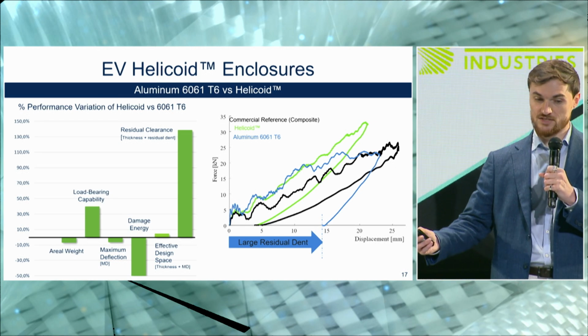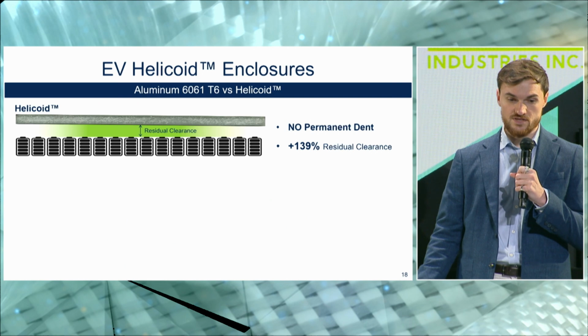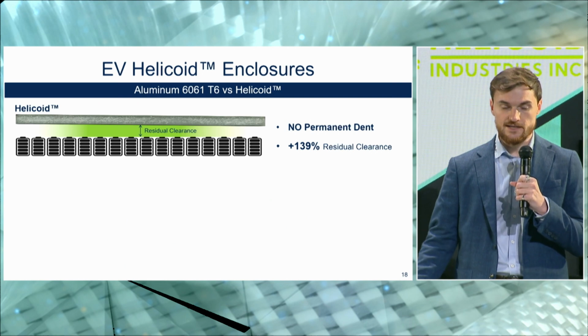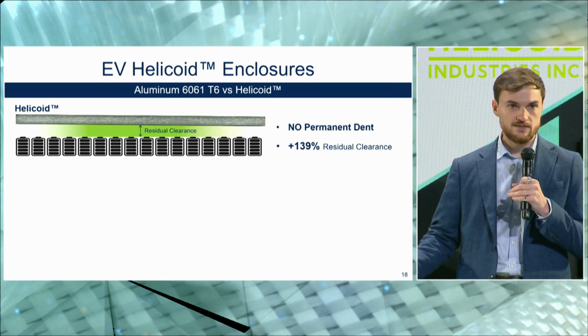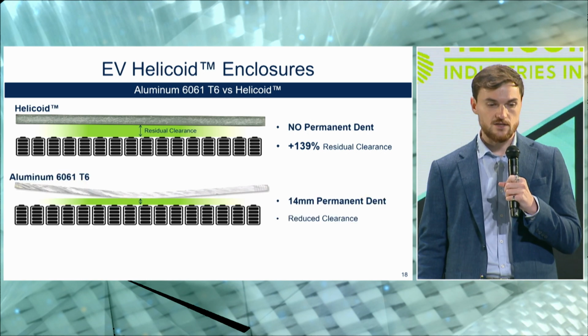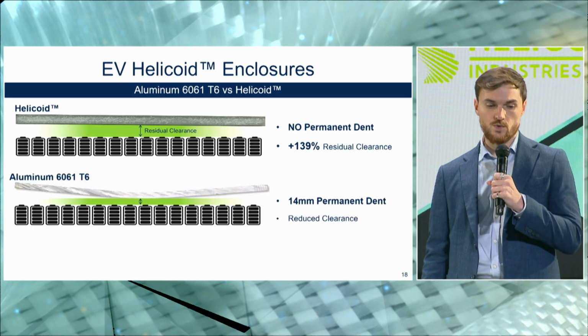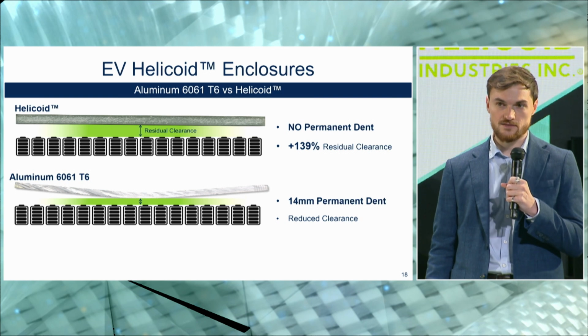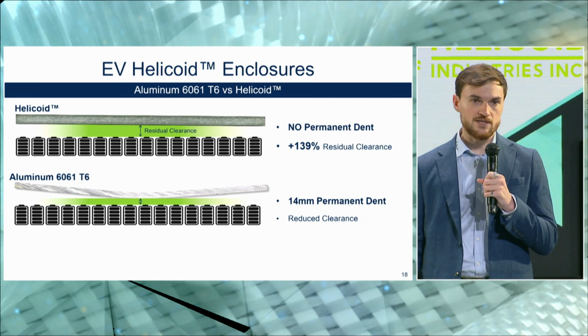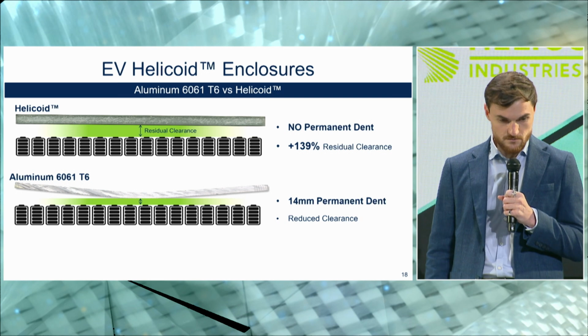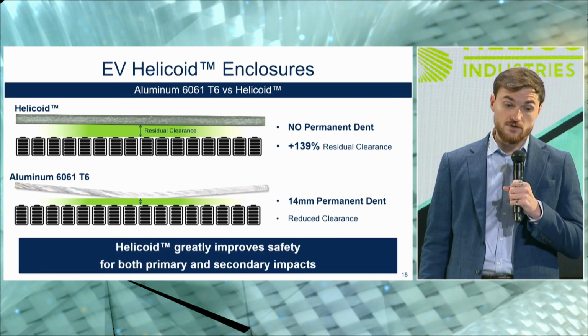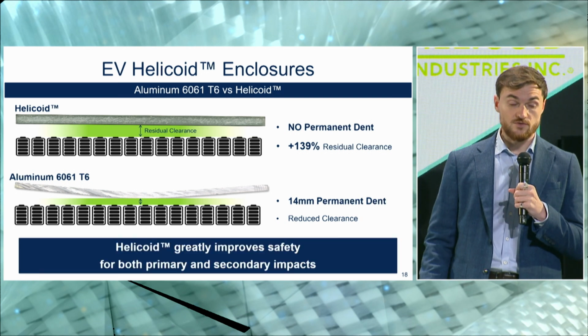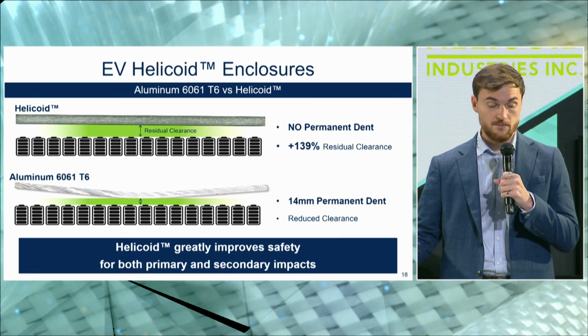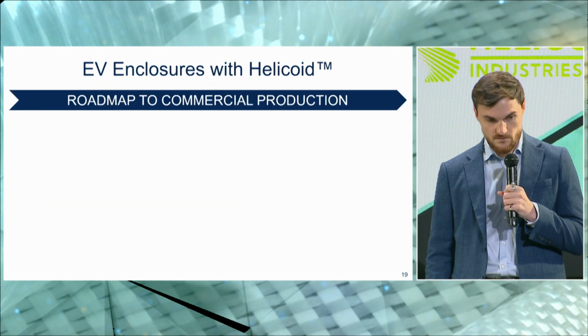Just for you to better understand, this is what residual clearance would look like in the helicoid. It basically goes back flat as it was originally, and this is the aluminum after the impact, where we have about 14 millimeter permanent dent. So you see that the clearance with the battery pack is very much reduced. So we deliver improved safety in this case for both primary but also secondary impact in the structure.